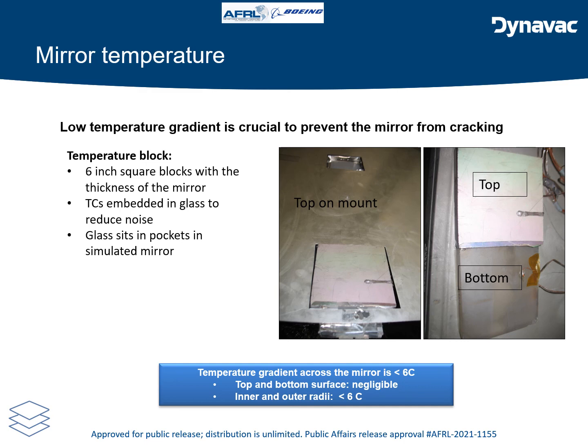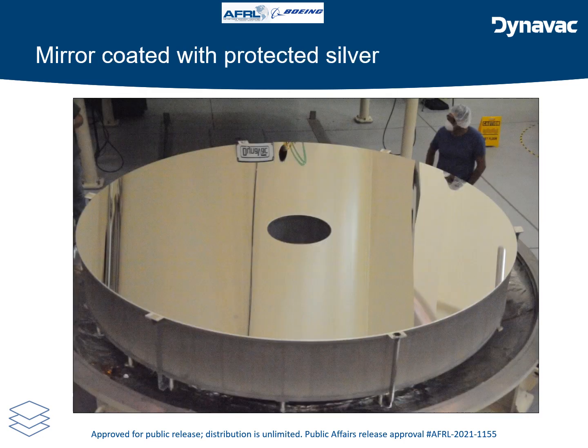The temperature difference between the inner and outer radii of the mirror was around 6 degrees C. This was acceptable, and hence we proceeded with coating the mirror with the actual protected silver coating. This is a picture of a coated mirror with protected silver. As you can see, it's a beautiful mirror with very good reflectivity. We can see the reflection of the coating chamber with the Dynavac logo in it.